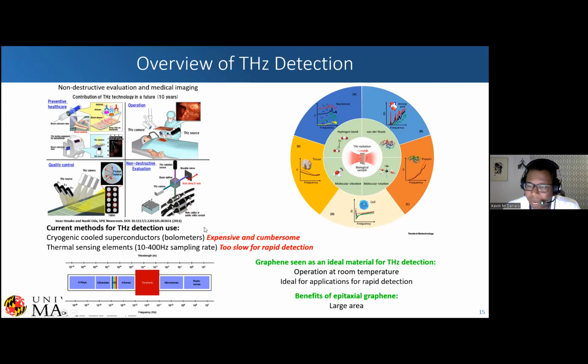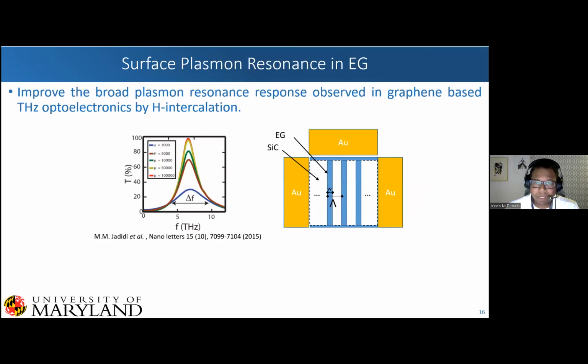And so this is where graphene comes in, because it is a semi-metal, and we can operate this at room temperature. It is ideal for rapid detection because instead of using a bolometer effect, we're using a plasmonic effect. And one of the benefits of epitaxial graphene is we're getting single crystal, very uniform material across an entire wafer scale, rather than flakes that you would typically get with exfoliated films, or even if we're talking about doing transferred CVD material. Now we're talking about materials with very small grain sizes, which can affect plasmon resonance.